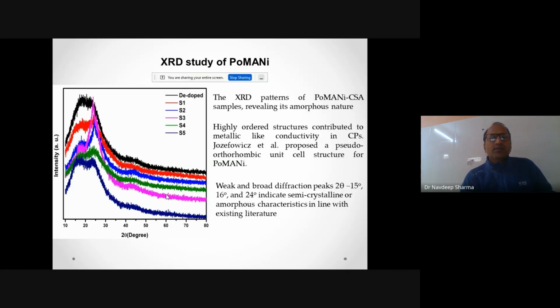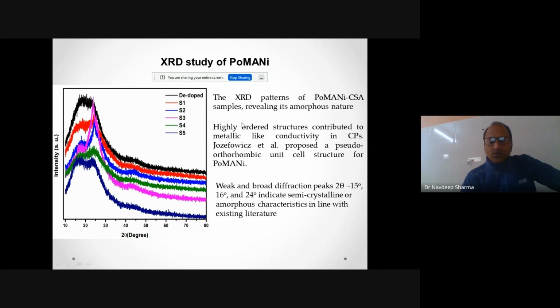The pattern, as you have seen here, of the de-doped sample, the black one, shows no peak at these positions. The broad diffraction peaks at 15, 16, or 24 degrees indicate a semi-crystalline or amorphous characteristic, as in the existing literature.